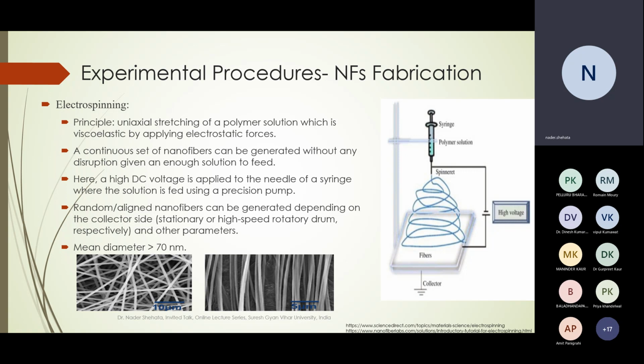on a normal metallic collector, or even a drum but with a relatively low speed rotation, then you will have randomly oriented nanofibers as shown in the left SEM. However, for the right SEM, here you can see mostly aligned nanofibers. It could be generated by different techniques, but one famous technique is to use a high-speed drum with a speed minimum of 3,000 or 3,500 RPM. Most likely, the formed nanofibers would be quite aligned, and it depends on the application that you will apply.